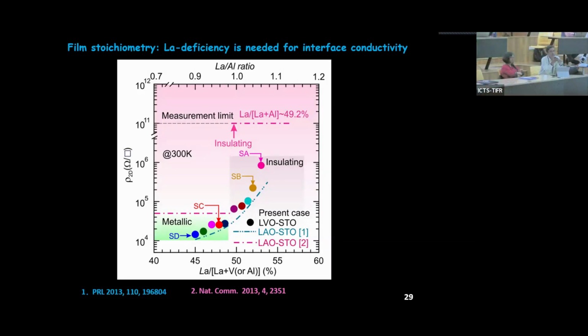Cation deficiency would inevitably mean you're doping the system. Cation deficiency in the film. Yeah. But if you see on the film measurement, it is not conducting. Only if you wire bond and go at the interface, it is conducting. You take the sample, you grow a thin film, the thick film, then you just put some wire with silver paste, it is not conducting.